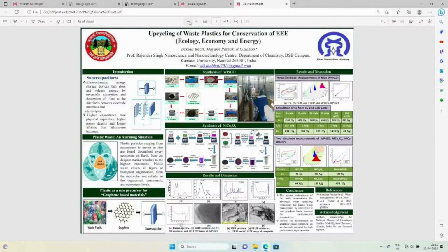After the first pyrolysis, we get the raw product, then we again place it in the tube furnace for the secondary pyrolysis, then we get the final product. Now this is the schematic representation for NiCo2O4, which is a bimetallic oxide, and making its composite with the waste plastic derived RGO. Here, this material is synthesized via hydrothermal method. These are the characterizations which confirm the synthesis of RGO from waste plastic, my bimetallic oxide and the composite material with the waste plastic. These are the Raman, XRD, IR and TEM data which confirm the successful synthesis of waste plastic derived RGO, my composite material and also the bimetallic oxide.